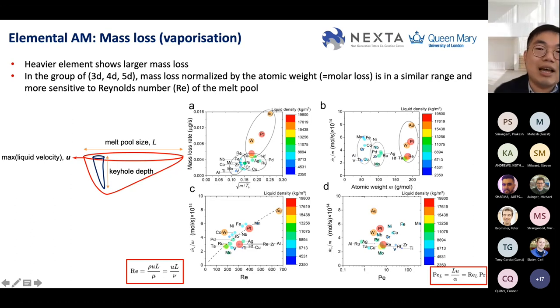And then we can see that it is chemistry dependent on the process, and then we can extract some trend of the mass loss. For example, heavier element, larger mass loss. The trend has a relationship with the flow, which we can't extract using traditional FE simulation if we're not considering fluid flow. And the trend in the diffusivity is not very clear. And that's why there's something called the Peclet number here.